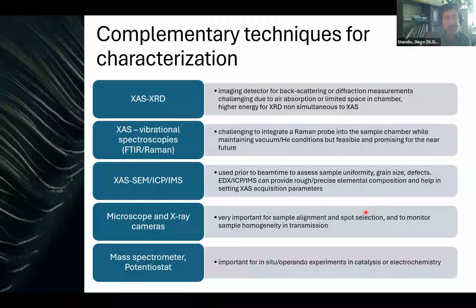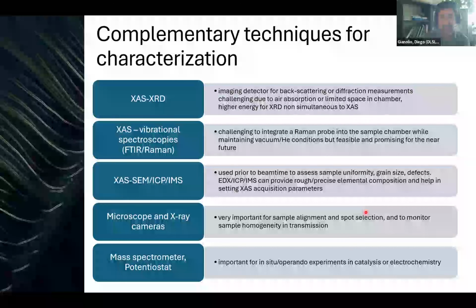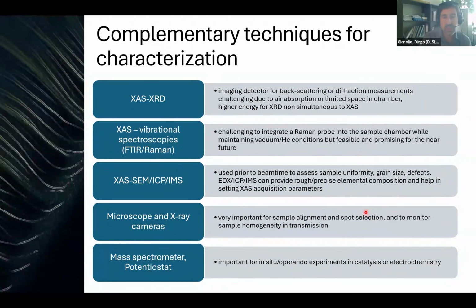And then apart from the sample environments, there is also interest in using other complementary techniques for the characterization of the samples. So here I included a few cases. The first two represent techniques that could potentially be used simultaneously and that give complementary information. For example, we all know that XAFS and XRD complement each other very well, because XAFS gives information more on the amorphous part of the sample, while XRD will give information on the crystalline part.